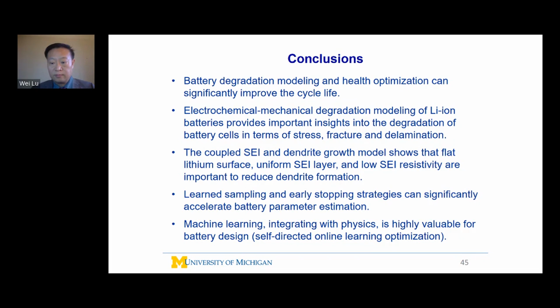Battery degradation is a complex issue. You mentioned various mechanisms at play. Which one do you see as the most critical factor in limiting battery lifespan, and how does your research address it? Thanks for the question. Many factors affect battery degradation. The specific dominating mechanism will depend on the battery chemistry. I would say for most of the current batteries, the dominating degradation mechanism is the SEI formation. So by looking at the factors that contribute to SEI formation, we can have a good understanding of how the battery degradation will evolve over time.